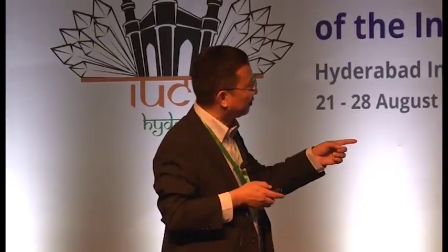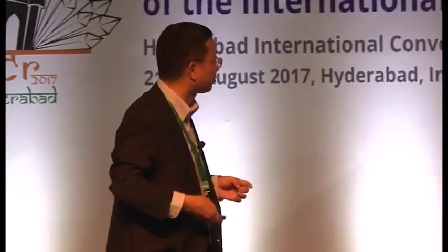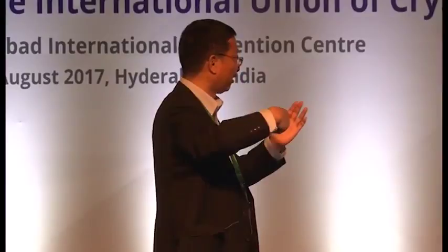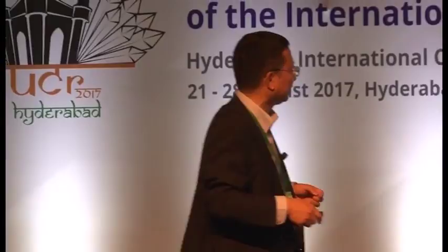Here we investigate a series of compounds like this to see what's the effect of equatorial ligands. I just show you can see chloride, bromide, iodide, these three compounds. Actually, for the three compounds, it's only the iodide coordinated in equatorial directions. We can see his hysteresis loop. It means the energy barrier for iodine is much higher than bromide and higher than chloride compounds.